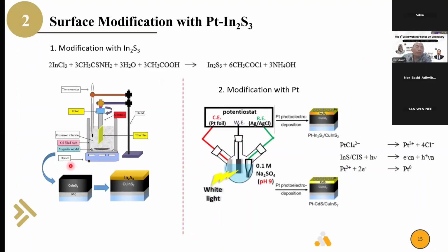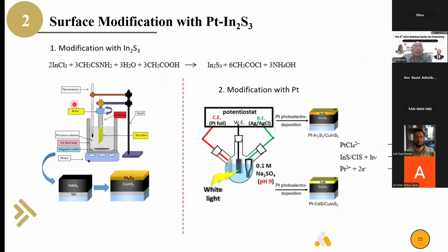So we use a water bath here to deposit the indium sulfide. This is around 70 degrees Celsius to deposit indium sulfide. And then we immerse the copper indium sulfide into the indium sulfide bath so that it will be covered with indium sulfide. This takes around 1 hour. So we call this chemical bath deposition.